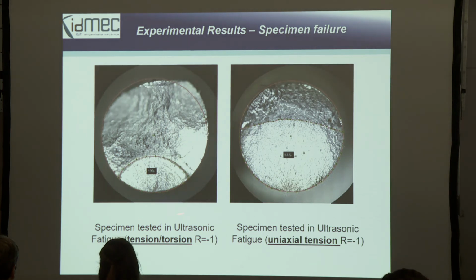So comparison, for uniaxial tension on ultrasonic fatigue, we have this behavior. We can never have a complete failure in ultrasonic fatigue testing, because when we have a larger crack, we lose the resonance of the machine, and the test stops. After this, it is broken in a normal uniaxial tension test. And for tension torsion, of course, this zone is much lower, because we have a conjunction of both stresses, and the shape of the crack is also different.